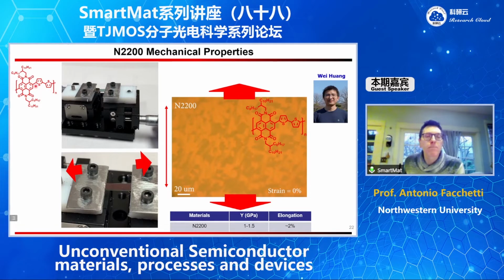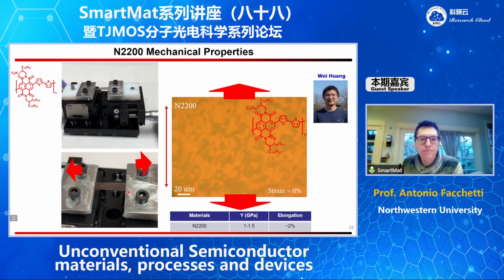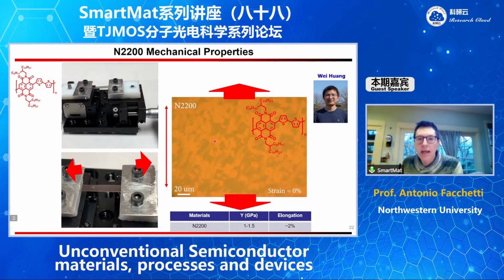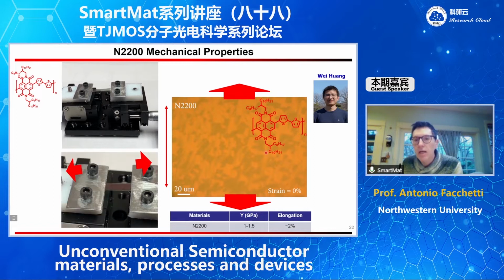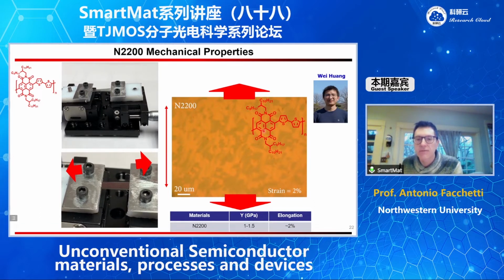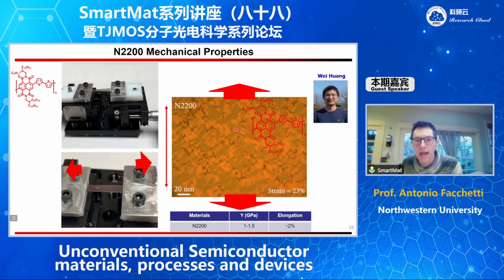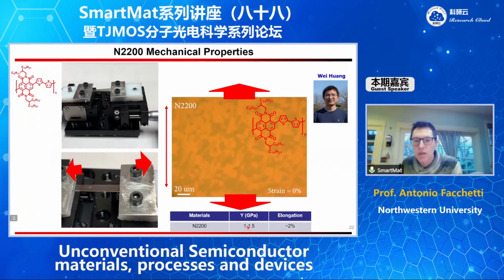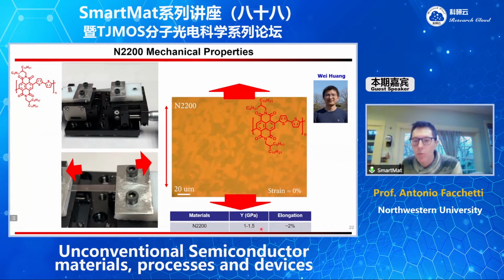Let me go back actually to the plastic properties of N2200. We can make films on elastomers and stretch them and measure some of the properties. And the film is not a very elastic film. You see formation of cracks here in the dark region. The Young modulus of this polymer is about 1.5, and the elongation at break is between 1 and 2%. So it's basically not a plastic polymer, with very small plastic and elastic deformations.